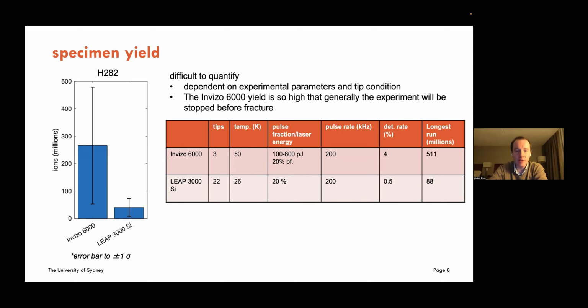And just some notes on specimen yield. It's actually a little bit difficult to quantify because it's dependent on the experimental parameters, of course, and the tip condition. And also because the yield on the Invizio 6000 in general is just so high that we generally stop the experiments before they fracture. So I guess that's the take-home message there, and from a practical point of view, it's looking really good. So, these Haynes 282 specimens, they're already running reasonably well on our LEAPs. We're getting into the tens of millions of atoms fairly regularly. We're particularly interested in crystallographic information, so those are run at cold temperature and voltage pulsing.